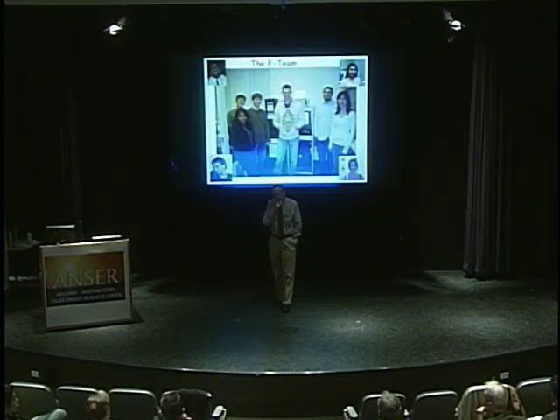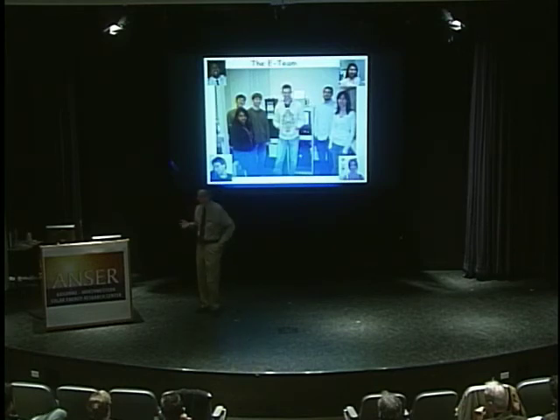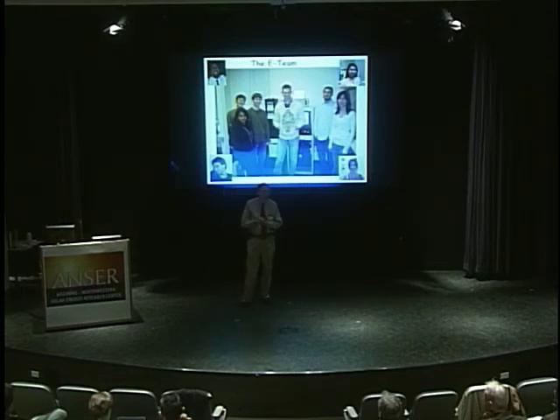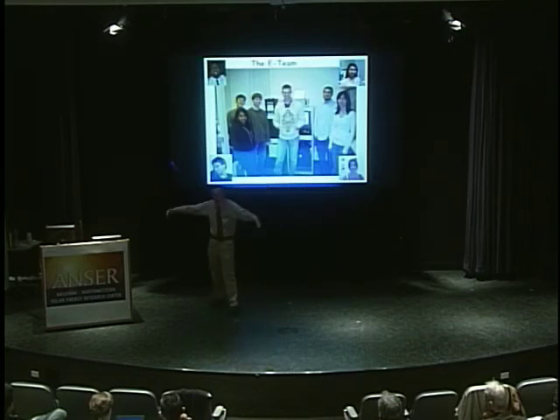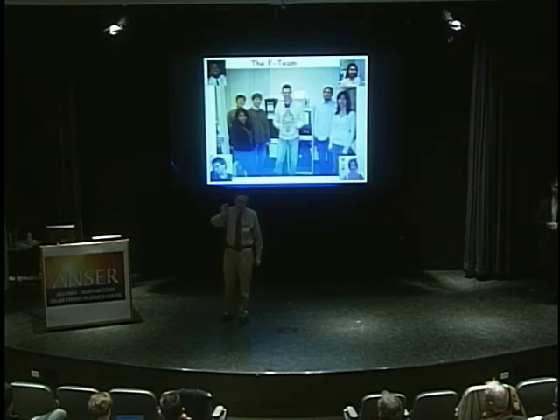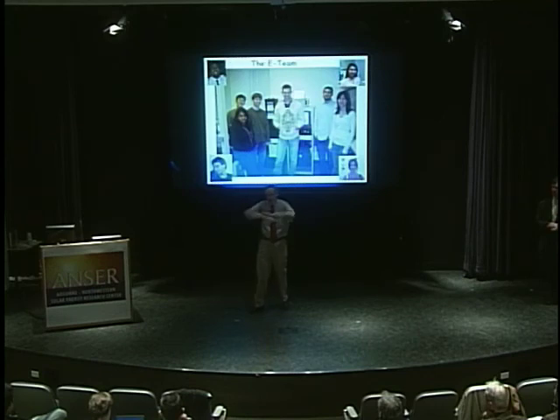What you find is commercial ITO varies enormously in quality, in sheet resistance, and some of it is just really awful. And I think it's mainly made by sputtering. The targets are about 4 feet wide by 8 feet long and a foot thick. So it's done on a huge scale, but I don't think it's done very carefully. And in fact, one theory for why you use PEDOT is that there are spikes in the ITO. And so you slather on a thick layer of some organic to smooth it out.